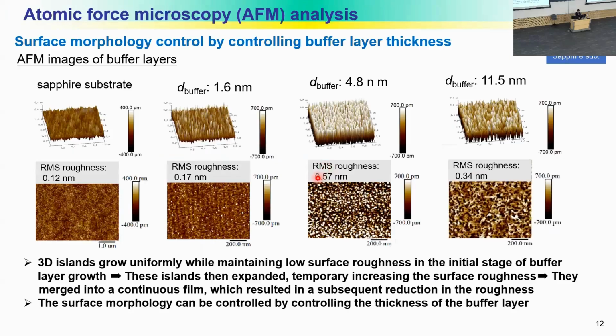This is an AFM image of the buffer layer. In this study, the surface morphology of the buffer layer was controlled by controlling the thickness of the buffer layer. The ZnO films were then fabricated on each buffer layer, and the relationship between the crystal quality of the ZnO film and the surface morphology of the buffer layer was investigated.